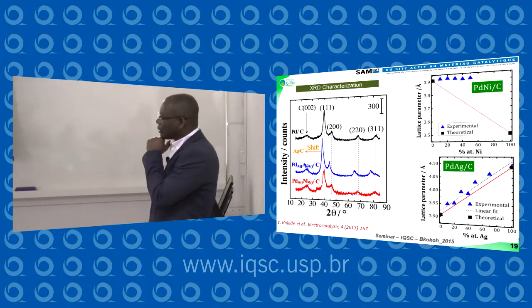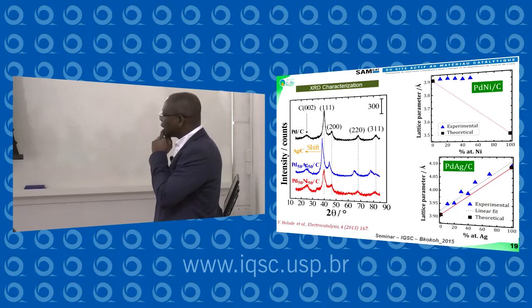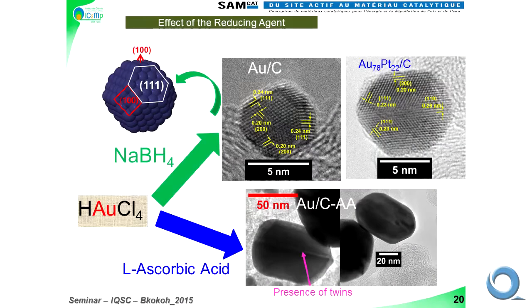And we have, consequently, an effect of the reducing agent. If we have sodium borohydride, can we change to avoid the insertion of hydrogen? We use, for the first time, ascorbic acid. This is a good reducing agent, and there is no hydrogen. The problem is the kinetics is very low. So when you take ascorbic acid, you have some larger nanoparticles, and we take it after because the surface is very clean, and we have no surfactant at the same time.